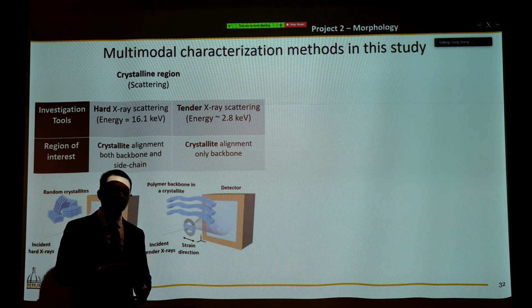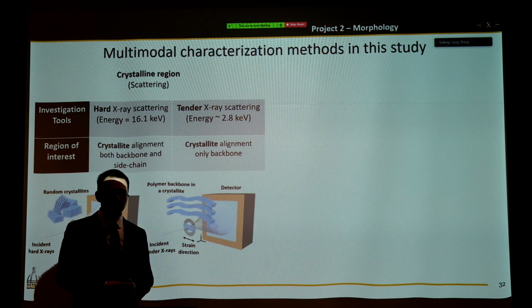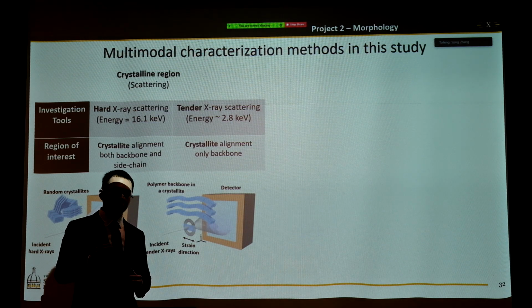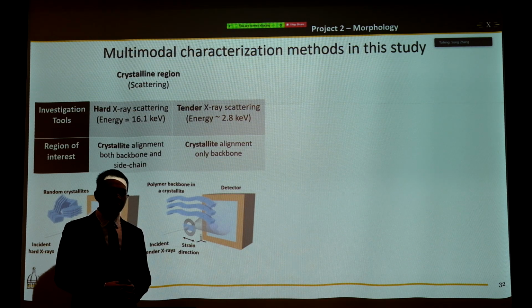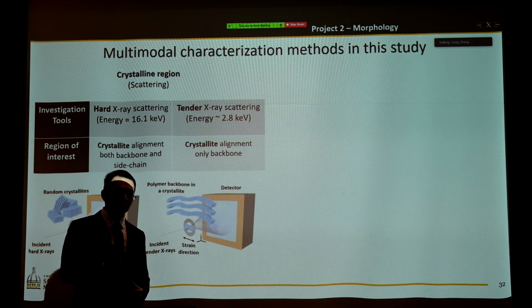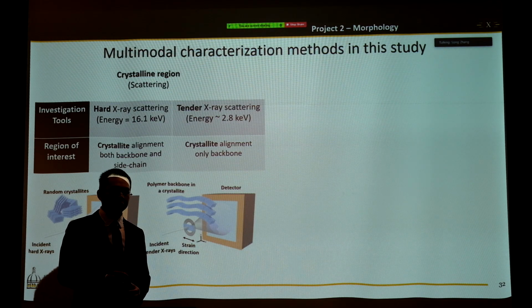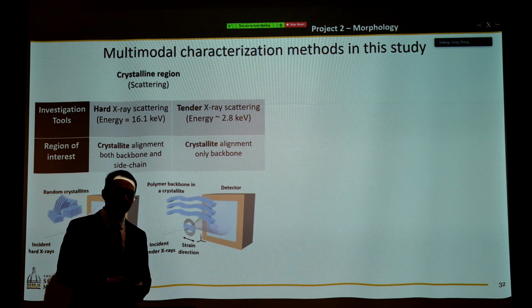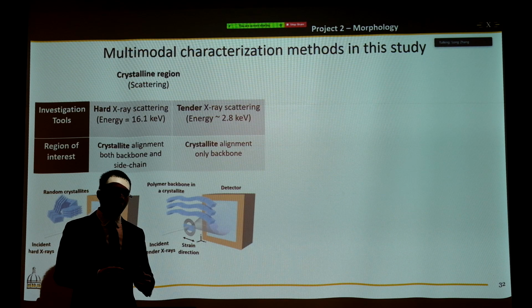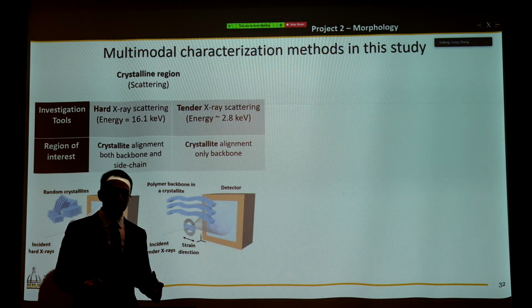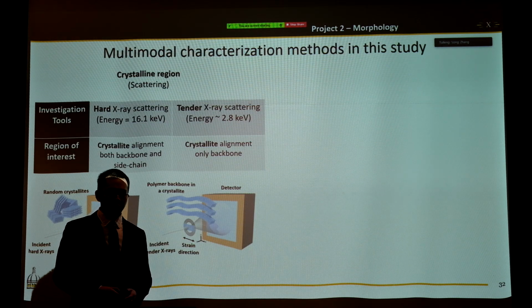And recently, there is a new technique called tender X-ray scattering, which can change the energy of X-ray to around 2.8 keV. And that allows only the sulfur atom along the polymer backbone to absorb this X-ray and scatter. So now we find a contrast between the backbone and side chain, which is the sulfur atom along the polymer backbone. And by using this technique, we were able to look at the backbone packing inside of these crystallites.